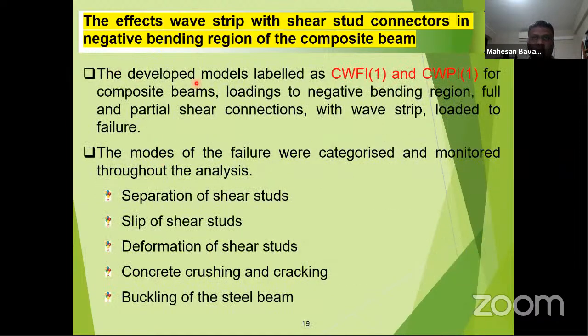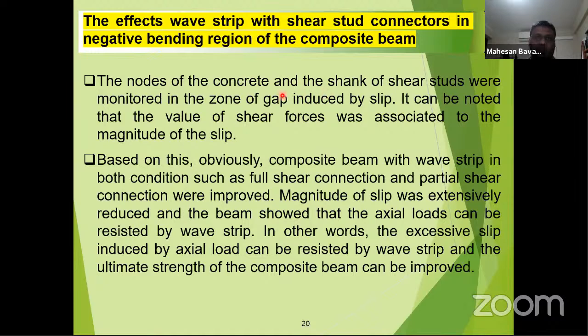So we developed this model, full and partial, and we focus on all the failure behaviors: separation of shear studs, slip of shear studs, deformation of shear studs, concrete crushing and cracking, and buckling of the steel beam. We check all the behaviors to see which one is the governing failure criterion in the composite beam at this stage. So the nodes of the concrete and the shank of the shear stud were monitored in the zone of the gap induced by slip. It can be noted that the value of shear forces was associated with the magnitude of the slip. So we are monitoring the magnitude of slip in the earlier condition and the current condition.